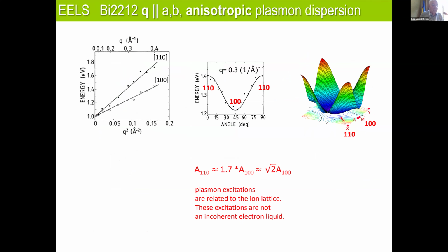Now, another important point is that we see an anisotropy of the plasmon dispersion. If you would assume that we have just an incoherent Fermi liquid, then we shouldn't see any anisotropy. But here we see this anisotropy, which means the dispersion is also determined by the interaction with the ions, and this means the dispersion is not determined by an incoherent electron liquid. When we look at this band structure, you see along different directions you have different Fermi velocities, and that's the reason why we see this dispersion.